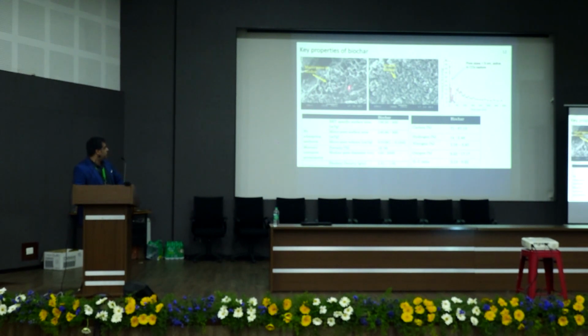So if you look under a microscope at biochar, which is not processed, you can see this kind of macropores on the surface. But this kind of macropores are really not suitable for use in concrete because that leads to drastic reduction in strength and durability. So we have to grind it to fine particles, and some particles can be in the nano range as well. But let's not be tricked into thinking that this kind of particles are not porous. In fact, they are highly mesoporous, with most of the pores in the size range of less than 10 nanometer or 20 nanometer, which is ideal for CO2 absorption. Why we use biochar is because of its affinity to absorb CO2 and improve the carbon sequestration potential in cement.